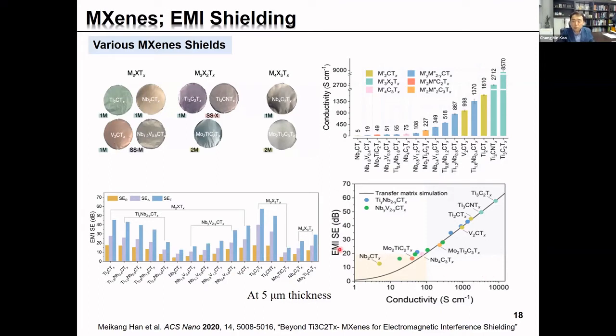Actually, they reported 16 different MXene materials' EMI shielding property. They found the EMI shielding property is strongly governed by the electrical conductivity. So the Ti3C2 MXene had the best EMI shielding property, and also that 16 different EMI shielding materials have a very broad spectrum in electrical conductivity. That means people can choose the right one according to the shielding level of their own purpose.